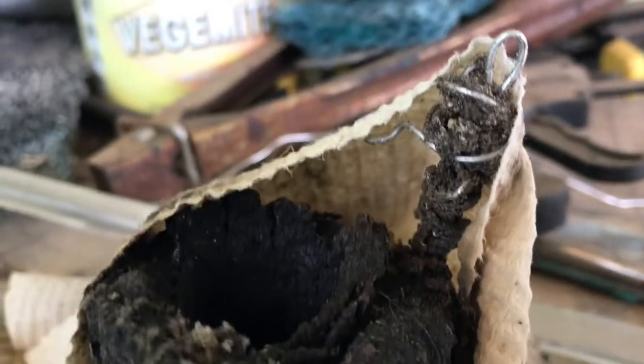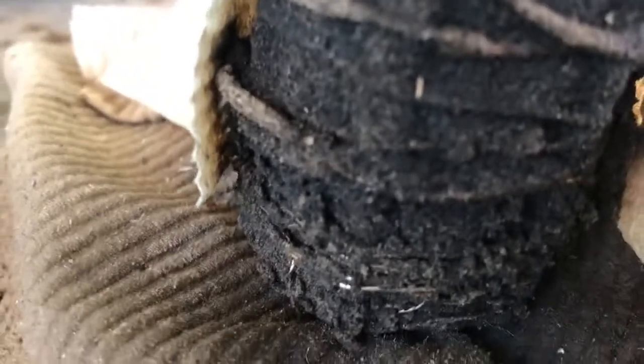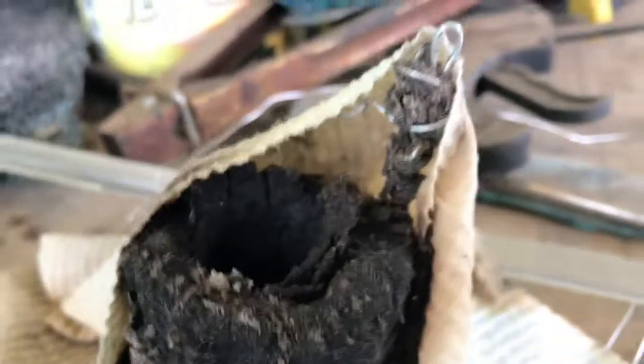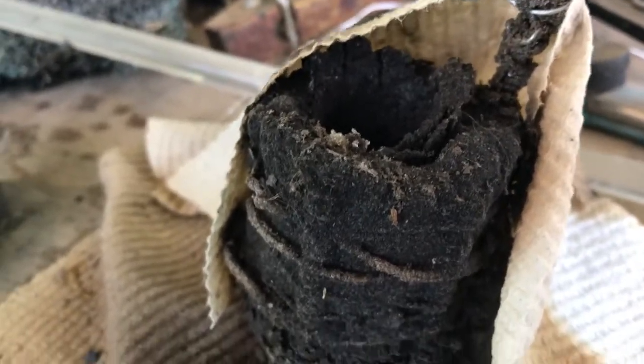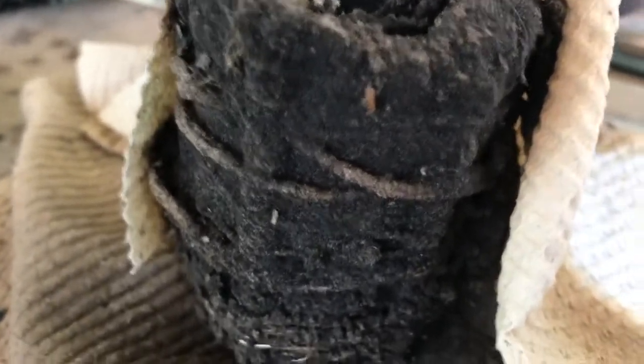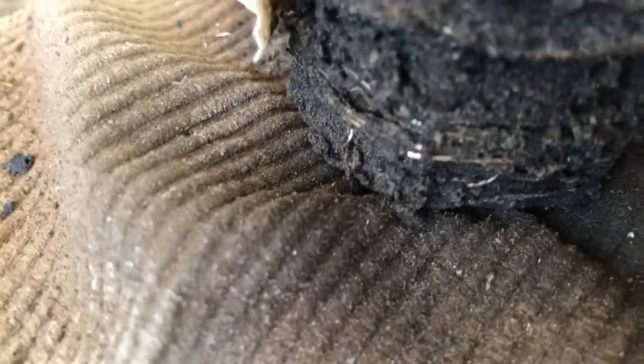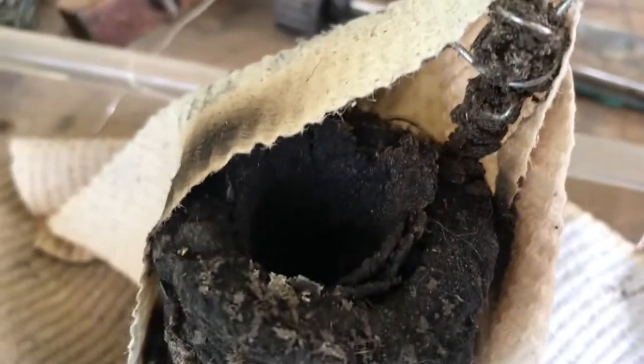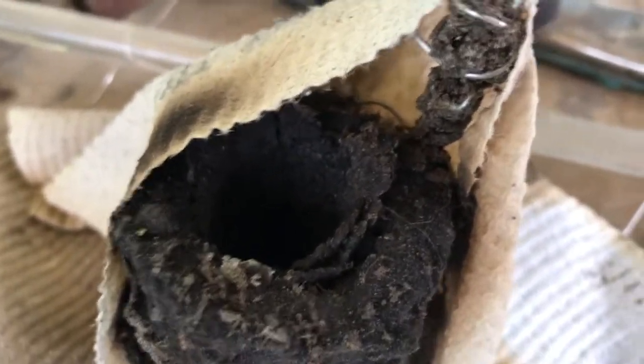So the reason I want 316 is that the wire around there is 316 grade, marine grade, and as you can see it's not corroded, that's just got plating around it. This cell's been in potassium hydroxide mix for over 3.5 to 4 years. And as you can see, that piece which isn't plated is still clean and contacting. All the rest has just got nickel coating probably. There's another shiny piece. And that cell still works. It does 3 hours at 100 milliamps. But I broke the center core now, so I can't test it anymore.